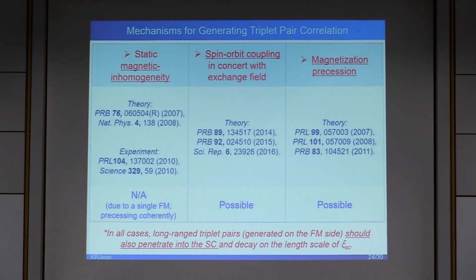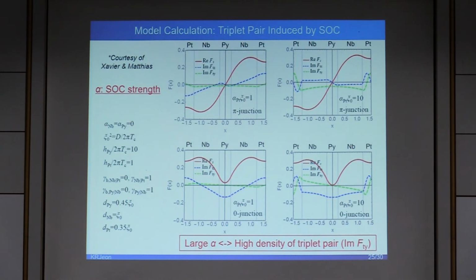Several mechanisms for generating spin triplet pairing state have been proposed. For instance, static inhomogeneous magnetization configuration, spin-orbit coupling in the presence of exchange field, or precession of interfacial magnetization. Because our sample structure contains a single homogeneous ferromagnet which is precessing coherently, the first mechanism appears to be irrelevant. The second mechanism may be able to generate the necessary triplet state if we assume finite spin splitting in the niobium layer, as supported by model calculation from our collaborators. Even if this model cannot yet quantitatively